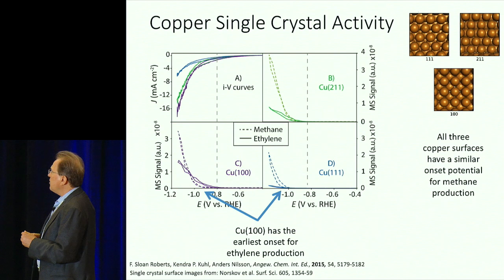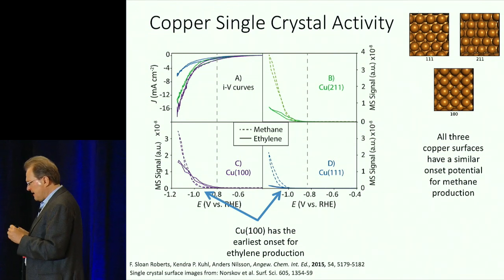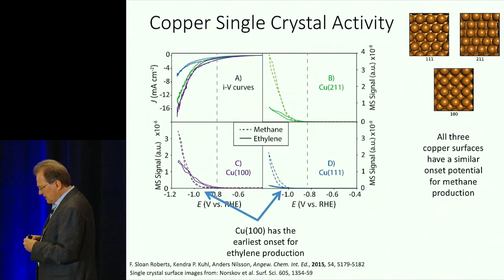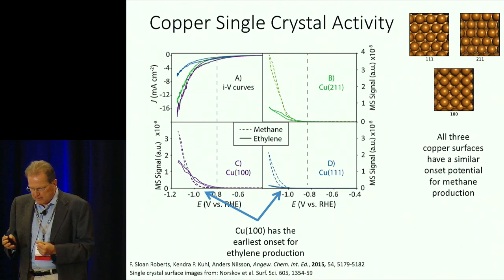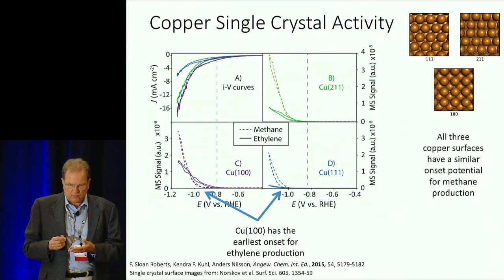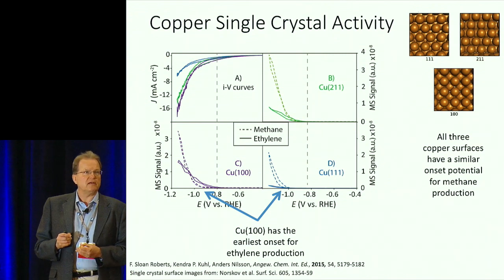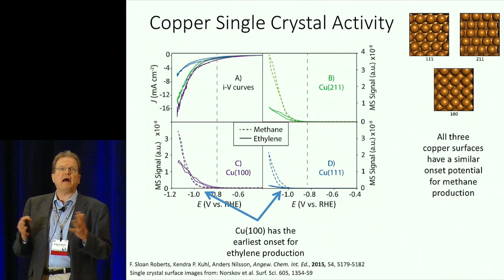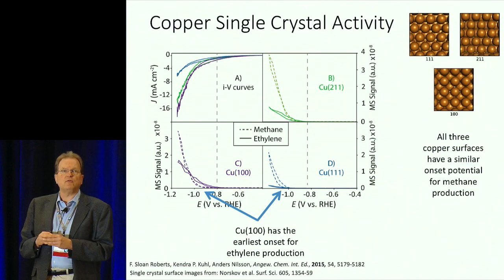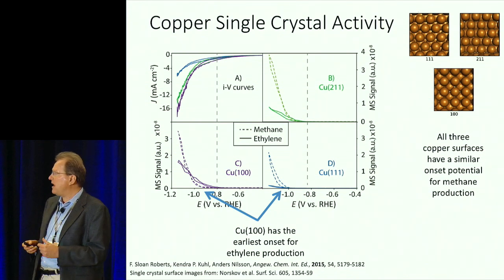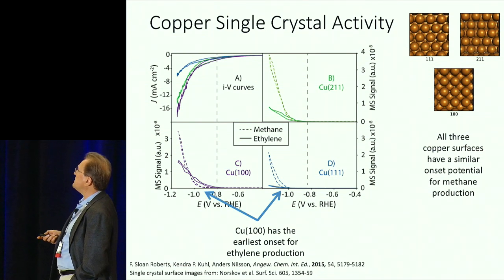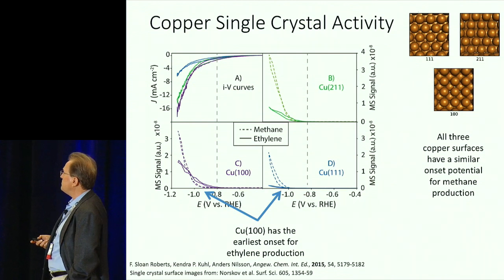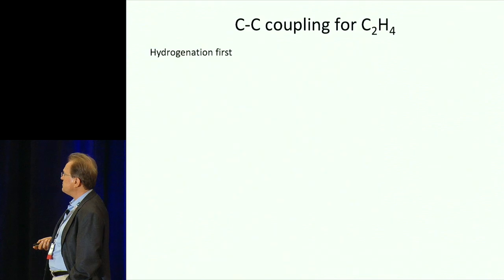And we can also look at all the different single crystals, and we can see that these cubes are very unique. When we compare how much ethylene is formed compared to methane, it's a change of a factor that varies, depending on how you do the measurement, between 10 and 100. We think in terms of the relative change of ethylene to methane. And none of that is even observed on different single crystal surfaces.